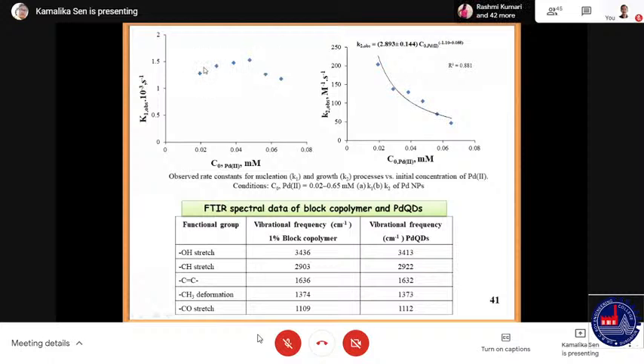The values are not changing much, but the K2 value that is dependent on the concentration of palladium is varying using this equation. The FTIR spectra of the block copolymer, when compared with that of the palladium quantum dots, we can see that they vary only little.